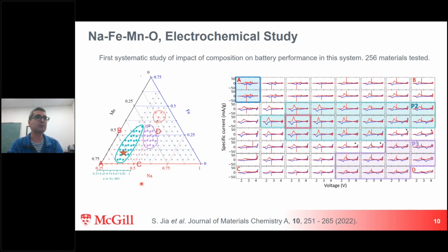So if we look at a material that sits on this binary here, it has no iron. And it has a lot of little peaks. So this material here, and even here, you still see these little peaks. If you do a lot of work, and this was already done in the literature, you learn that these little peaks are phase transitions. So as the sodium is being removed and put into the material, the structure is changing. It's not robust. And over time, that leads to bad cycling. So the capacity, the energy that you can store goes down dramatically with time.